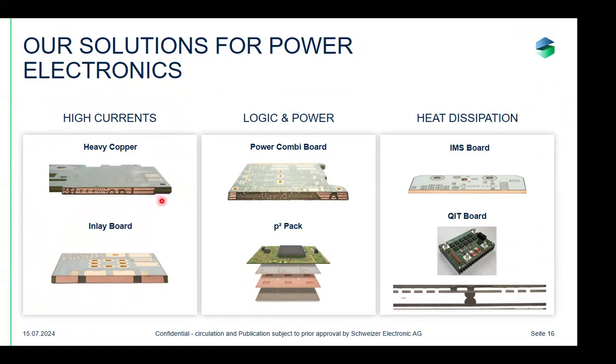With the heavy copper, you use standard materials, but with thicker copper platings on the inner layers. The maximum thickness could be up to 400 microns. The cross section that you see here is 4 times 400 microns. So you have a total cross section of 1.6 millimeters of copper inside one PCB, which is quite a bit.